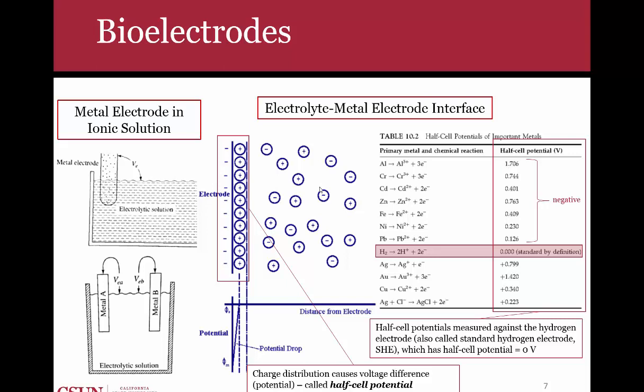For instance, on the right here you have a table called half-cell potential. Half-cell potential is what I just mentioned. It's the voltage that's produced across the interface of the electrode metal and the electrolyte because of a separation of charge. For instance, if I highlight aluminum here, if I dunk an aluminum rod into an electrolytic solution, then I'm going to get a voltage across that interface of negative 1.7 volts. That's a really large voltage produced at that interface. So if I put my reference electrode, or the reference part of the multimeter, in the electrolyte, and attach the other end to the metal, I'm going to get a voltage difference of negative 1.706.